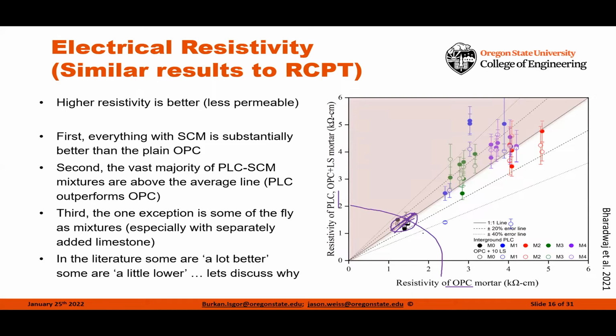But the big thing I want us to do is take a bigger picture out and look at this overall graph. These systems down here that I circled, the systems in black, are the plain OPC or the plain PLC that we have in our system. There's no SCMs added. As we start to move to the right-hand side, what we notice in either the blue mixtures, which are fly ash, the red mixtures, which are fly ash with silica fume, the green mixtures, which are fly ash and slag, and the purple, which is a natural pozzolan, all of these show a substantial improvement in the resistivity of the system.